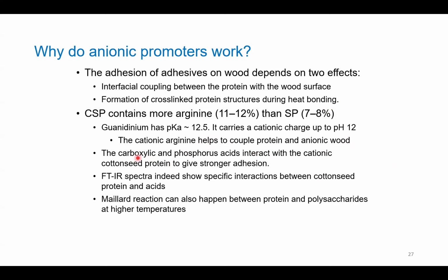And by adding additional carboxylic acid like anionic polysaccharide, and phosphoric acid also works, it interacts with the cationic cottonseed protein in order to give it a stronger adhesion. And indeed, FTIR shows that there are specific interactions between cottonseed protein and the carboxylic acids. Of course, in addition, the Maillard reaction can happen between protein and polysaccharides, and it will enhance the strength of the materials even more. So this shows that indeed we can find replacements for formaldehyde resins using cottonseed protein.